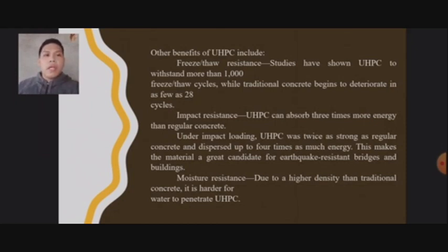Under impact loading, UHPC was twice as strong as regular concrete and dispersed up to 4 times as much energy. This makes the material a great candidate for earthquake-resistant bridges and buildings. And next is moisture resistance. Due to a higher density than traditional concrete, it is harder for water to penetrate UHPC.